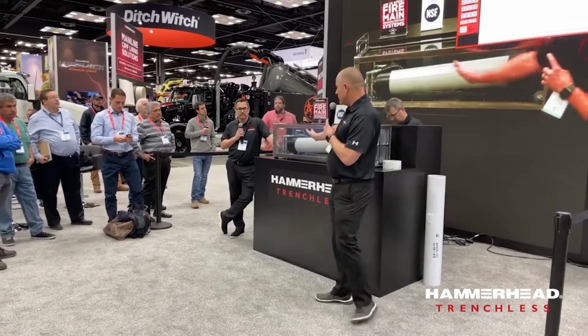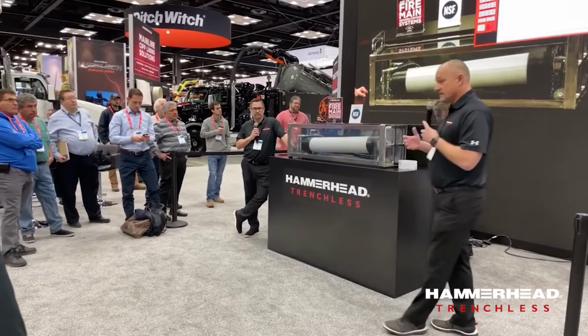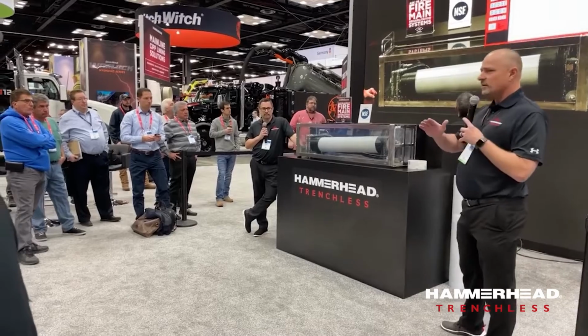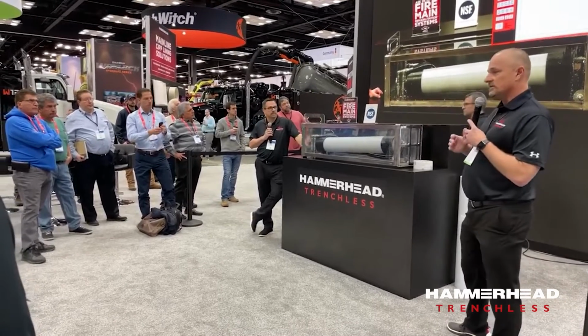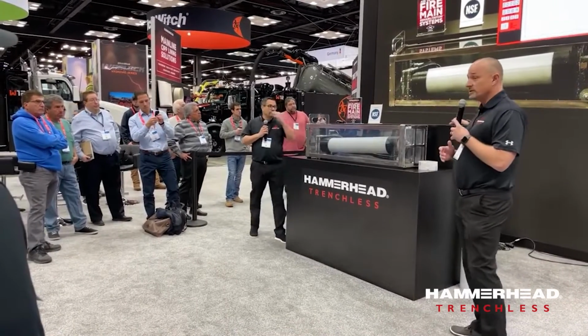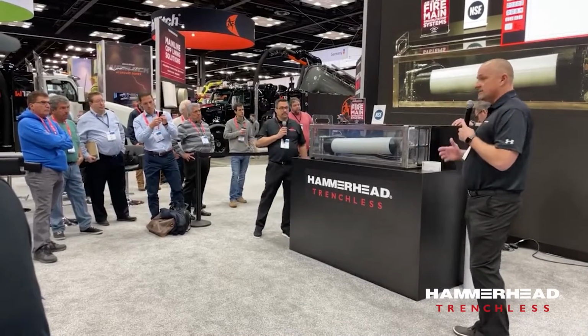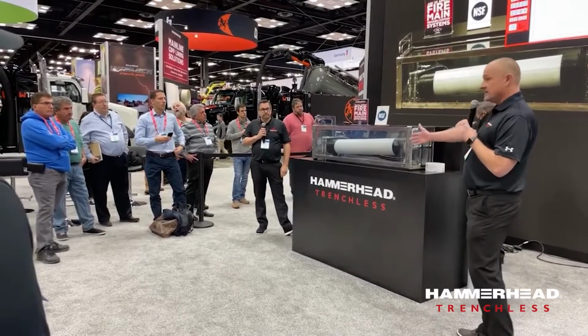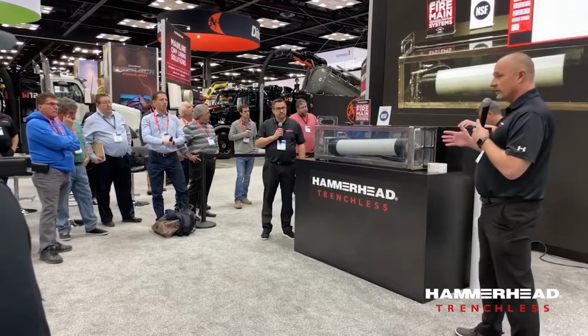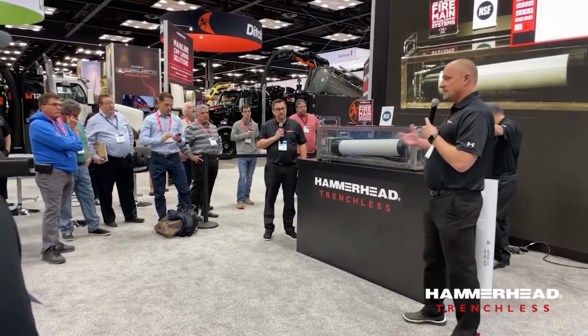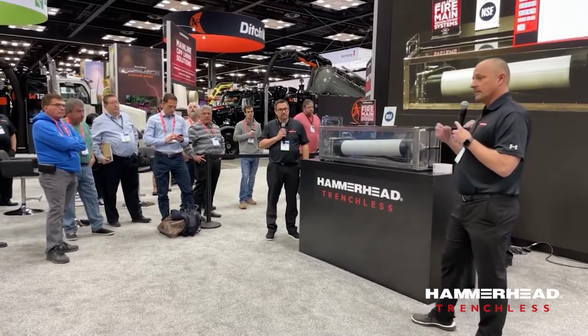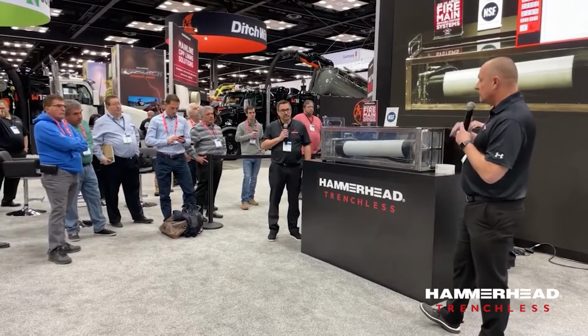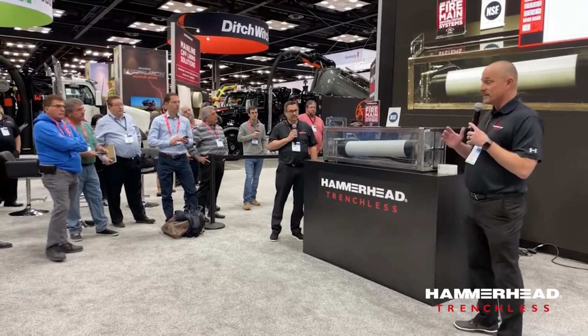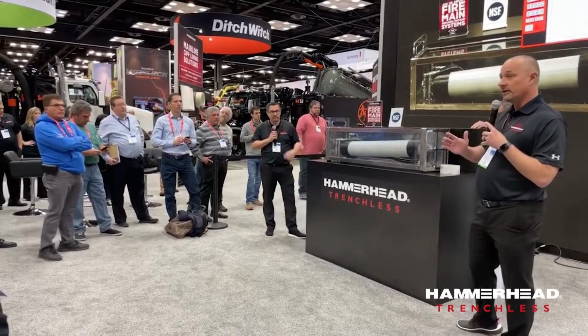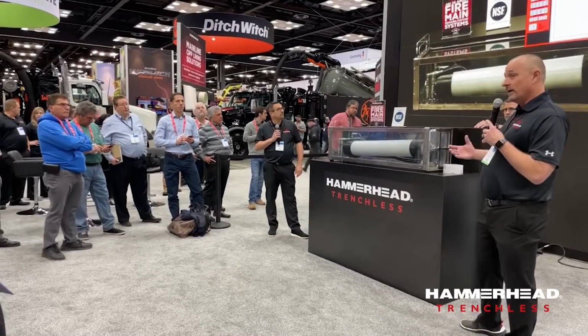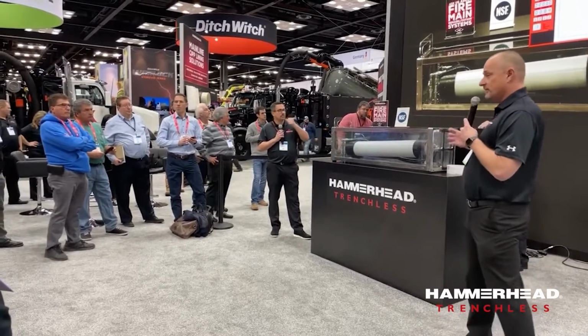What we're trying to do is pressurize this system, again, at a steady rate over a short period of time until it reaches failure. And depending on the type of material you're dealing with, whether it's a thermoplastic or a thermosetting material, in this case a reinforced thermoset with epoxy resin, you're going to see a physical burst. So it's going to be a pop. It's going to be a punch through type burst. You could see materials that will have a linear failure, or it could be in a spot, or it could be a weep. But in this case, it's going to be a physical burst.